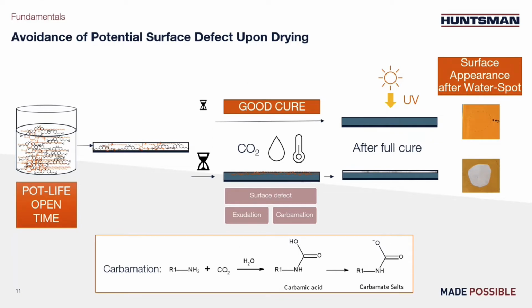So after cure, you have the case with no surface defect still on the top. And when you perform a water spot test, meaning leaving a drop of water for 1 hour and removing it, there is no trace visible afterwards.